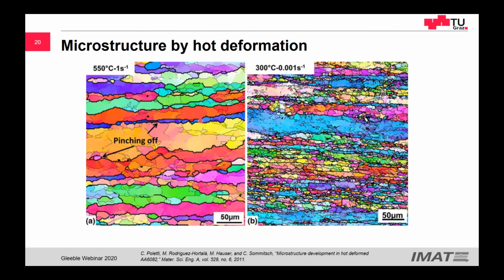So during hot deformation, we have formation of cells of subgrains. And the lower the temperature and the higher the strain rate, the smaller these substructures are. And since we are doing rolling, we are squeezing the grains, and by squeezing the grains, we may also have something called geometric dynamic recrystallization, which means the high angle grain boundaries, the black lines here, meet together and produce new grains. Of course, you need very large deformations for it.